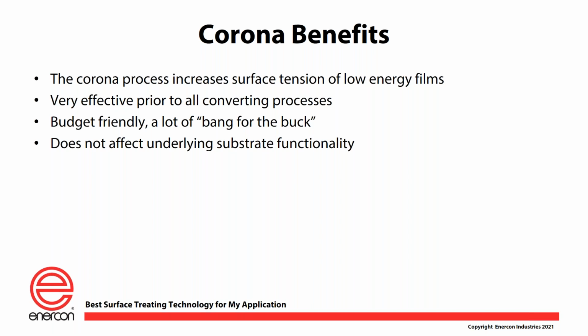Now, to give you some context here, most converting inks and coatings will operate just fine. They will wet and adhere really well at a dyne level in that 40 to say 44 dyne range. So we don't necessarily need to treat the film to some extraordinary level. We just need to get it from its inherent value, what it is when we get it, up to an area that's more commensurate with whatever the liquid is. Corona treaters are very effective for all converting processes. So whether you're printing, coating, laminating, whether your technology is solvent, solventless, UV curable, or E-beam curable, whatever it is, the corona treater can effectively treat the substrate prior to it going into your process.